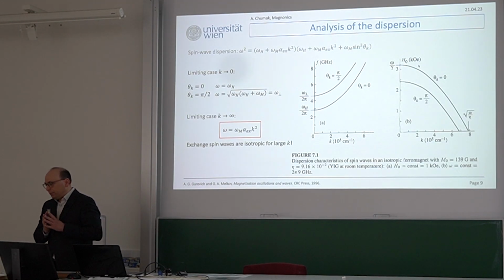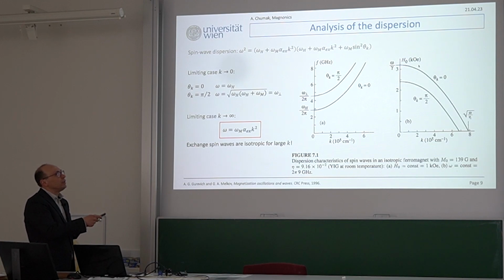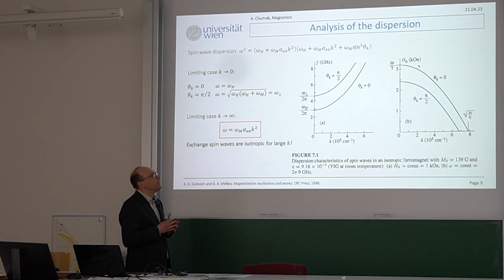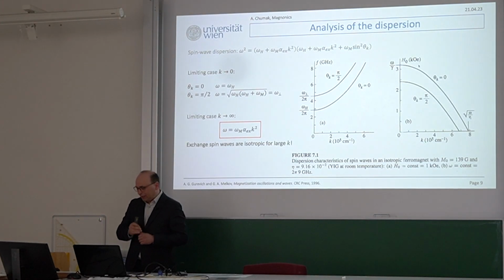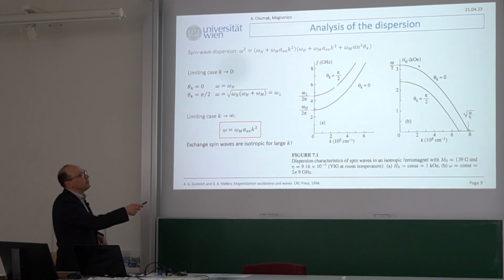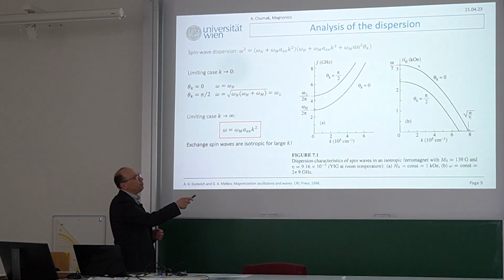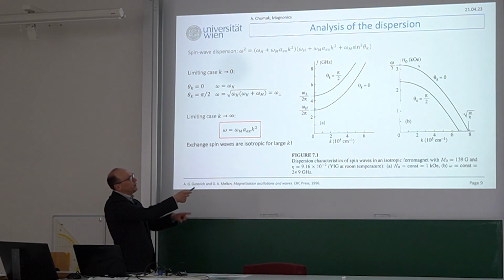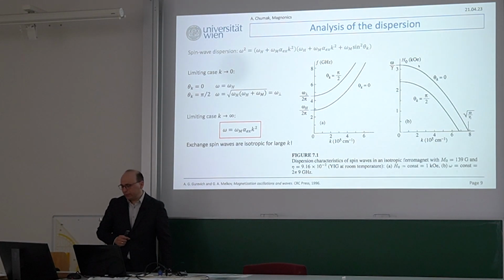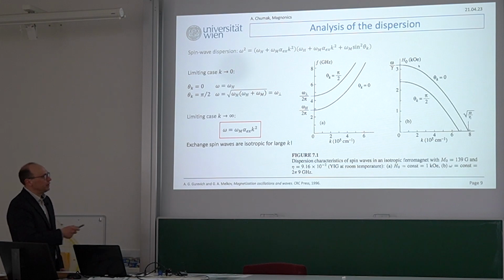And please keep in mind that this is not only two dispersion lines. When we discuss, next lecture, magnetostatic waves, one line means one dispersion. Here it's a different picture. Here it means that all this is a band. So what is shown here is the top and bottom of the band where exchange spin waves exist. But in each part of this band, you have different angles. So this is theta k, which runs along magnetization, and this one which runs perpendicular to magnetization. But in between, you have dispersions for all other waves, which have some other dispersions. Good.